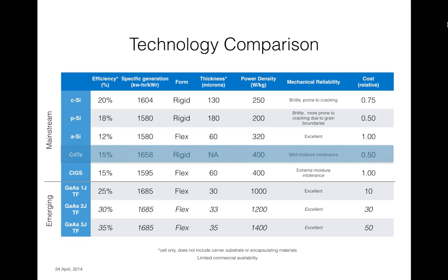You'd rather just add more payload, put in more battery, and solve the problem that way. And so, really, for me, the tipping point for making solar useful, just looking at energy density or power density, is somewhere north of 1,000 watts per kilogram. And just anecdotally, I'll tell you, on a 2.5 meter wingspan aircraft, you can get about 130 or 140 watts of solar at that energy density onto an aircraft. And when you look at a 2.5 meter wingspan airplane weighing in at 30, 40, 50, 60 ounces, 125 or 130 watts of power is a meaningful amount of power.